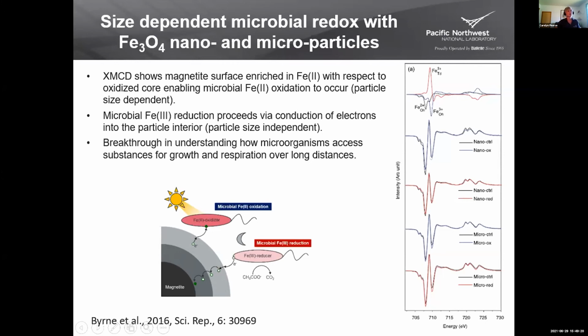And his work showed by using XMCD and fitting that data that the iron oxidation was relatively easy because iron 2 was localized at the surface, but then the iron reduction required the conduction of electrons into the particle interior, and so that was much more particle size independent, whereas the oxidation, which was very localized to the surface, was more dependent on the available particle size. And so we can really use this information to understand how microorganisms can access these redox active minerals for growth and respiration over long distances.